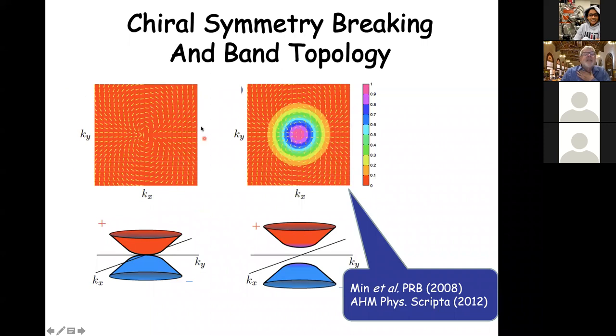That phase difference has a momentum dependence and some topology, which is inherited ultimately, of course, from the single layer graphene sheet. And that is that in these valley projected bands, I'll come back and emphasize valley again in a moment, the phase difference between the layers winds by 4 pi in momentum space when you go around a circle in momentum space. So this is a kind of vortex with vorticity 2 in momentum space of the bands.